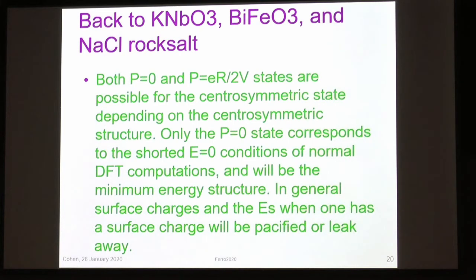So I maintain that in the centrosymmetric materials, both the zero polarization and this half a quantum polarization lattice are both realizable in an electronic structure calculation. And only the P equals 0 one corresponds to the shorted, electric field equals 0 conditions of normal DFT calculations. I'll finish up and allow a few minutes for questions. And this has been known for a long time. In fact, even when you have charged surfaces, it's known that they get passivated in real materials, or the charge leaks away, and in the end you end up with a zero charge state.